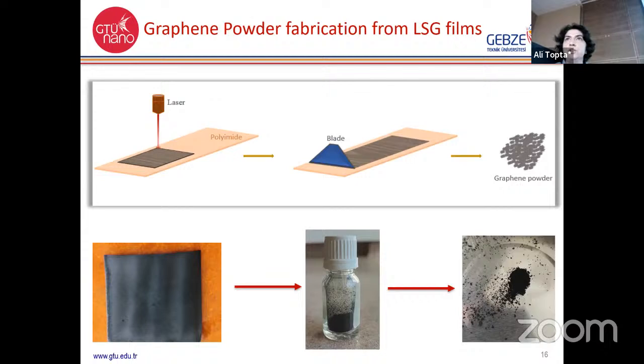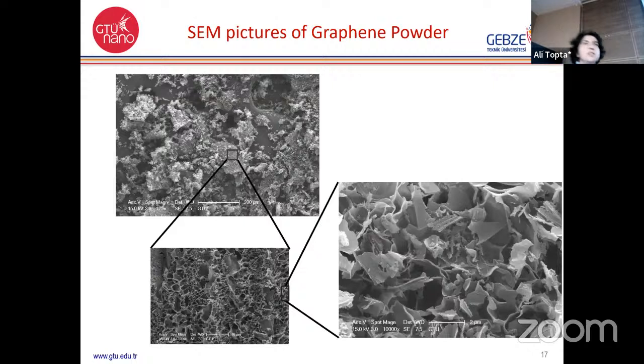Currently, we are working on how to make these big chunks smaller. And the first thing that we tried was simple mechanical grinding, okay? And that worked beautifully. Even that one brought the flakes down to around 2 microns in width. So that's really good, because we still have a thickness of a few nanometers.